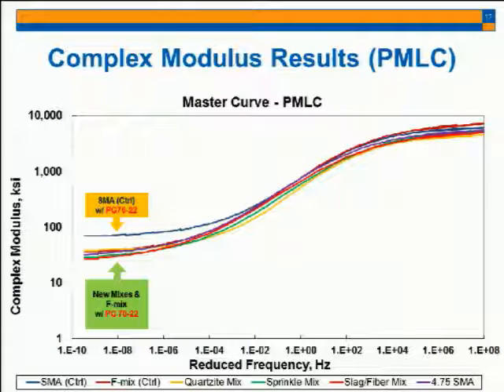So as you can see here, this is the master curve of the 6 mixtures. It's a plant mix and lab compacted specimen. From the complex modulus, we can generally pick up two points, here and here. This point is more related to the fracture performance. It's the low temperature and high frequency area. So here it's high temperature and low frequency. It's more related to the rutting.